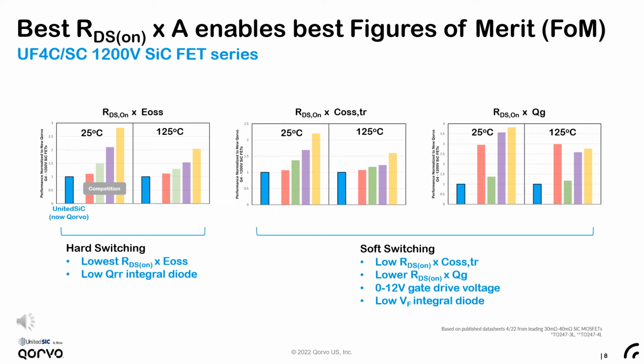In this chart, we show the new 1200 volt Gen 4 FETs alongside their peers at room temperature and 125 C. Their lowest RDS(on) times COSS and low QRR of their integral diode make them attractive for hard switching. And also looking at the RDS(on) times COSS time related and low QG times RDS(on), along with their lower VF of their integral diode and their very low conduction losses, make them nearly ideal for the soft switching applications, such as the primary side of isolated DC-DC converters.